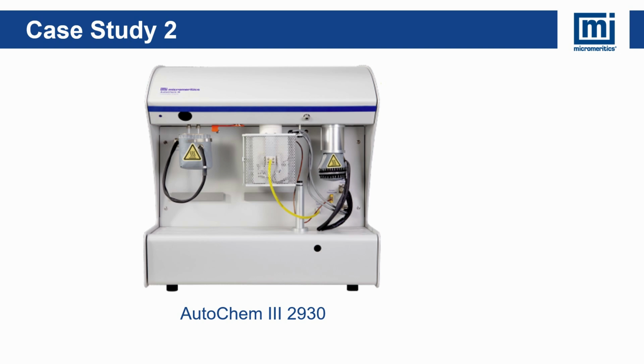That was the first case study using the static chemisorption method on our 3Flex. Now we'll move on to the second case study, in which we investigated the impact of oxygen on metal dispersion measurements using dynamic chemisorption method on our AutoChem III. 2 experiments were conducted. The first was a controlled experiment, and the second involved an additional step where we removed the sample tube and exposed it to air for about 1 hour after the activation step.